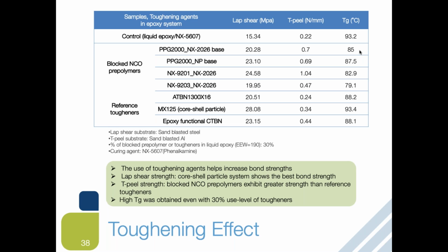When you think about the 30% addition of this type of product, you would expect more of a TG reduction, but the blocked pre-polymer has shown very good, high TG. I believe this is achieved mainly because when blocked polymers are mixed in this system, ultimately they chemically react with the epoxy and amine system. So it does not stay as a non-reactive diluent, it stays as a reactive plasticizer or modifier. That resulted in a higher TG.